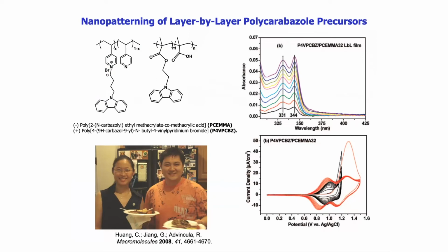Now, in terms of polymer synthesis strategies, we did make a lot of new polymers that can be patterned this way. Corresponding here is that of a polyelectrolyte, polycation and polyanion, polyvinyl pyridine and polyacrylic acid, bearing a carbazole electropolymerizable monomer. Now, we can deposit this as thin films, alternating between the negative and positively charged layer, which can be monitored by the increase in absorption over this UV-vis spectra.